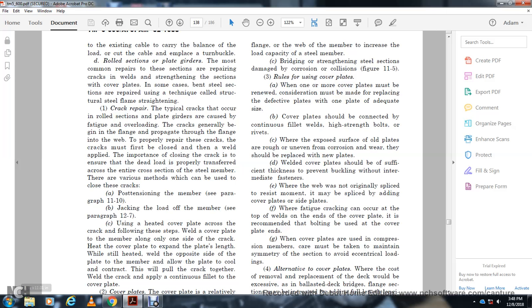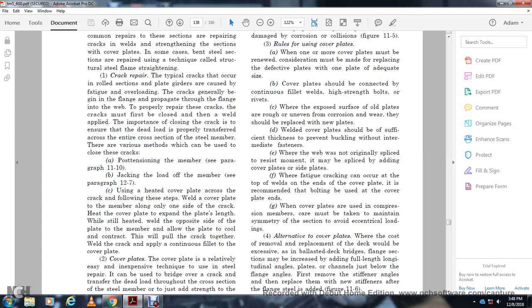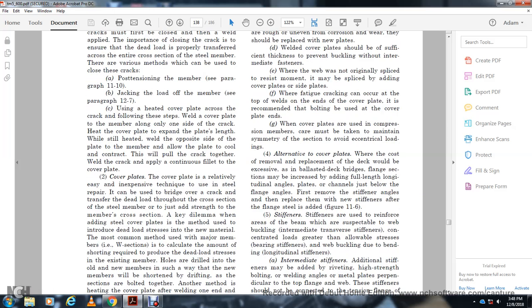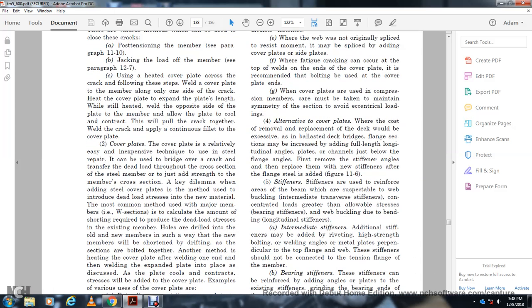When using a cover plate to repair a crack, heat one end of the plate with a welding torch while the opposite end is fixed, then allow the plate to cool and contract — this will pull the crack closed. Apply a continuous fillet weld. Cover plate repair is relatively easy and inexpensive. The cover plate can bridge over the crack and transfer the dead load throughout the cross-section of the steel member. However, adding a steel cover plate introduces dead load stress in the new material.